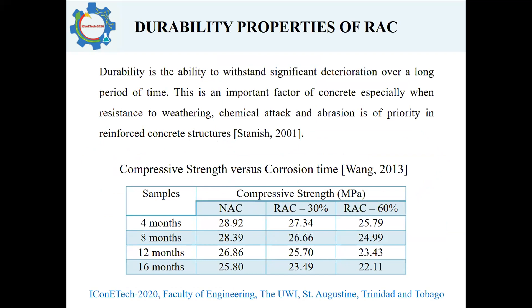Within this example, recycled aggregate concrete specimens were cast and compacted into 100 millimeter cubes and allowed to cure for 28 days. After 28 days of curing, all specimens were submerged in seawater for eight hours and removed for 16 hours every day to simulate a tidal zone in the marine atmosphere. It was found that with an increase in recycled concrete aggregate replacement and a longer duration of exposure to seawater, there was a decrease in compressive strength as compared to the natural aggregate specimens, as shown in the table.